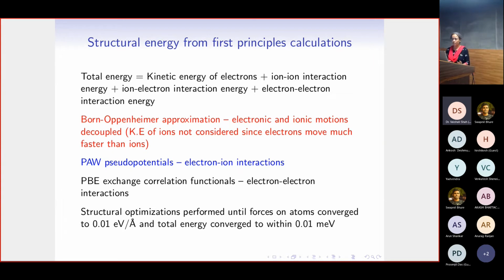And with this, now we perform the structural optimizations for aluminum, zinc, and the aluminum zinc alloy, for which we are interested in obtaining the solid-solid interface energy. So we do the optimizations until the forces on atoms are reasonably well converged, and the total energy of the system again is reasonably well converged.